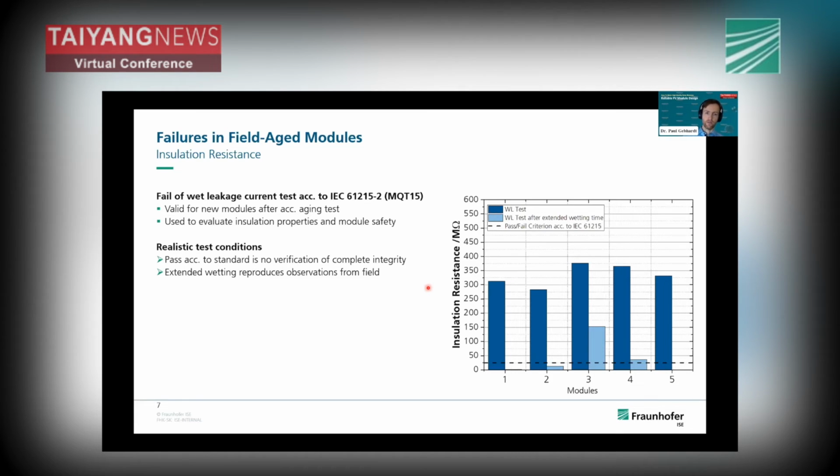Therefore, we concluded that it's necessary to extend this wetting time, and one reason for this might be that the modules simply dry out, for example, in the storage or the transport time right before the test that we perform in our lab.